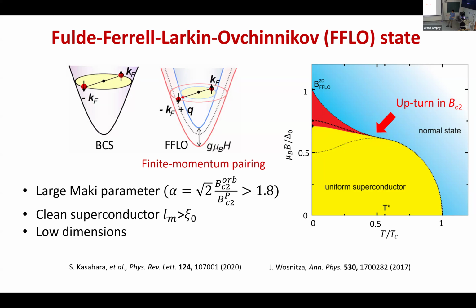Of course, other mechanisms can induce this. So one needs to check, for example, that you have a really clean superconductor. If you induce some disorder, you may kill this upturn. Secondly, you need to check that there is a first order phase transition across this boundary. Usually there's some thermodynamic evidence, like heat capacity measurements, to demonstrate this. And finally, if you really want to prove this, you need to measure especially if you have some modulation of your order parameter. But I think so far nobody has done this. It's very hard to check this.